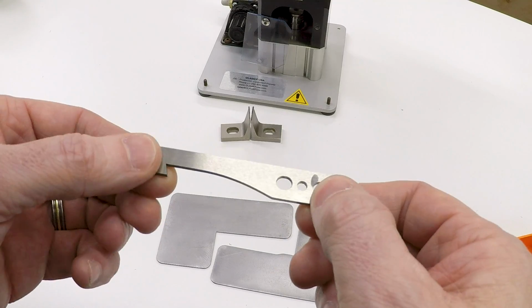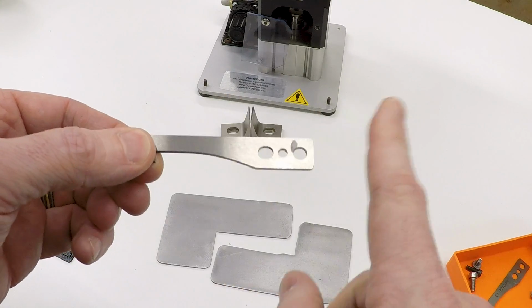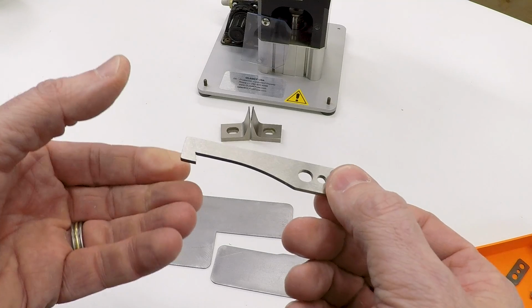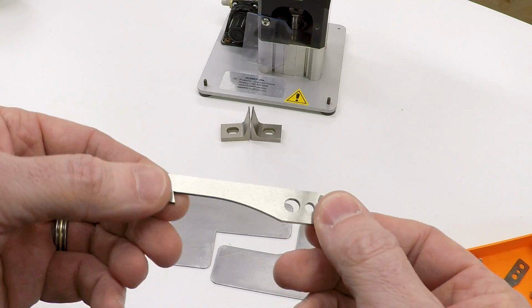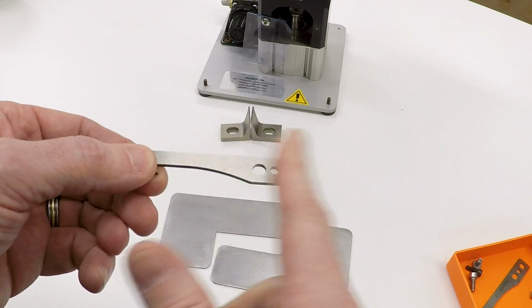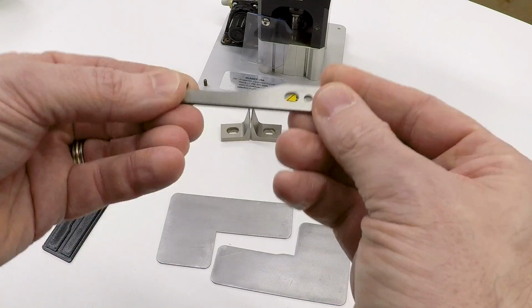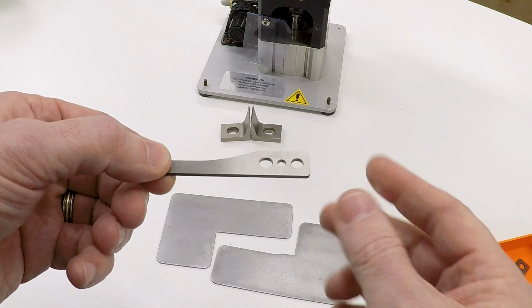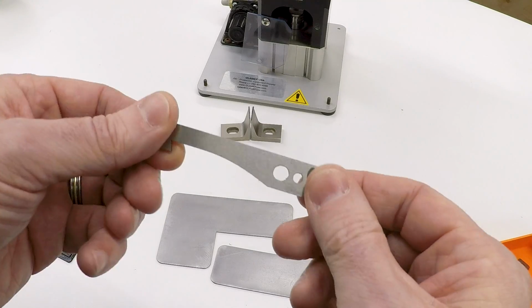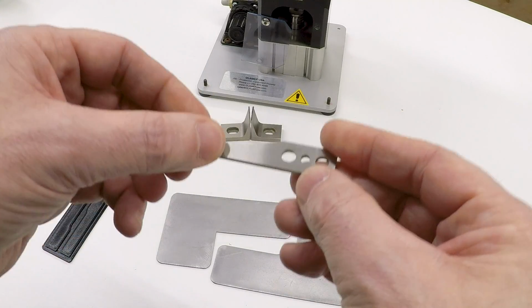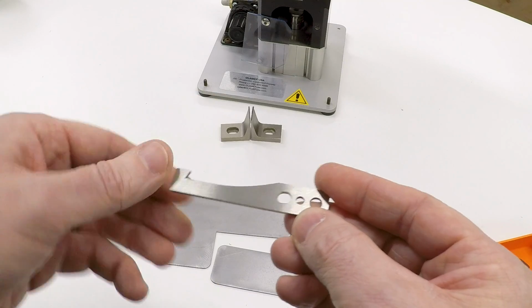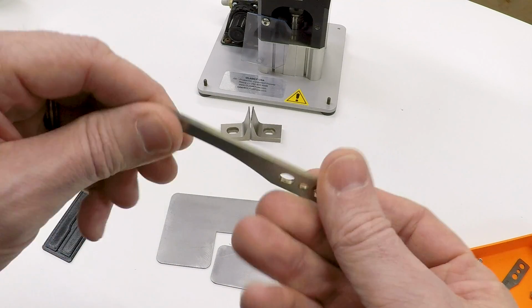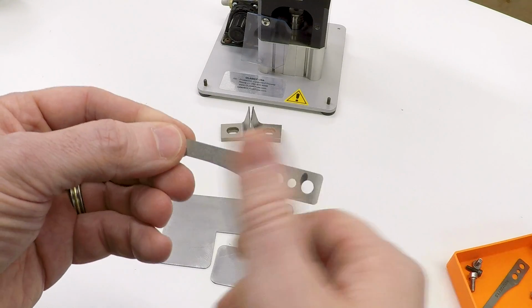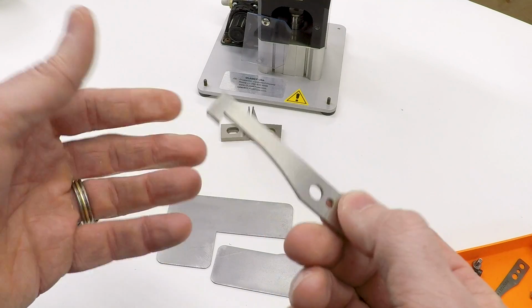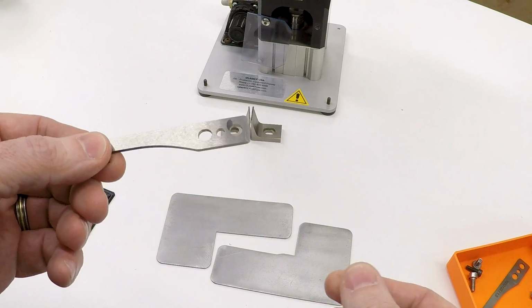But what we discovered is that as you grind material off of one side, the part started to cup to that side. So if in multiple passes you took it down 2 thou and then put that on the surface plate, you could put a 1 or 2 thou feeler gauge under the middle of it because it bowed that much. But then if you flip it over, suck it back down on the magnet flat, take the same 2 thou off the other side, it straightened back out. So as long as we took the material off evenly, the part stayed straight, certainly straight enough for this application.